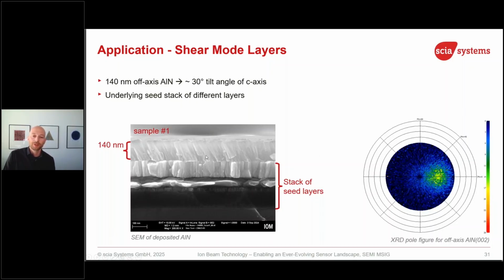How do we know that the crystals are tilted? Of course, we see it here in the SEM, but we can do it also in XRD. Here we have a pole figure showing us the crystal orientation, and there's a maximum here at 30 degrees. It's not super sharp, but we investigated it, and there's no benefit if we make this peak much sharper. So that's a great result, and we see very nice preferred orientation for our aluminum nitride. So with those layers, one can build biosensors activated in this shear mode.